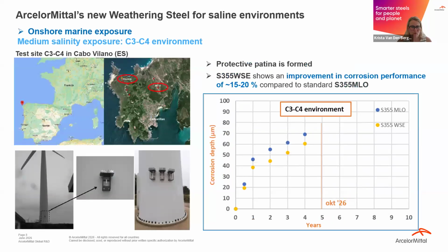So if we move then to a more severe environment, where we have C3 up to C4, it's an exposure we have in the north of Spain, where we have more chlorides, and here the exposure is on a wind farm. If we look at the corrosion performance, it is expressed as material loss over time, so you can express it in corrosion depth or the corrosion rate. And we see here after 4 years that we have a lower corrosion rate of the saline-resistant weathering steel, up to 20% compared to the reference construction steel.